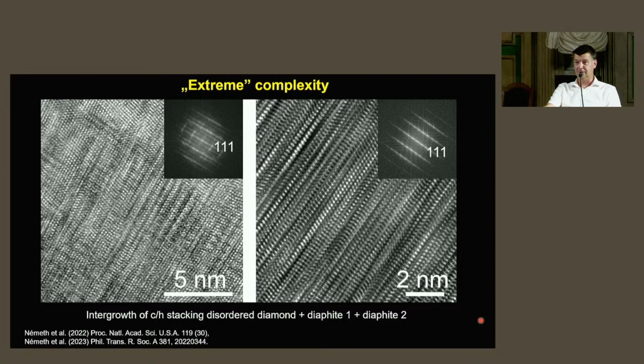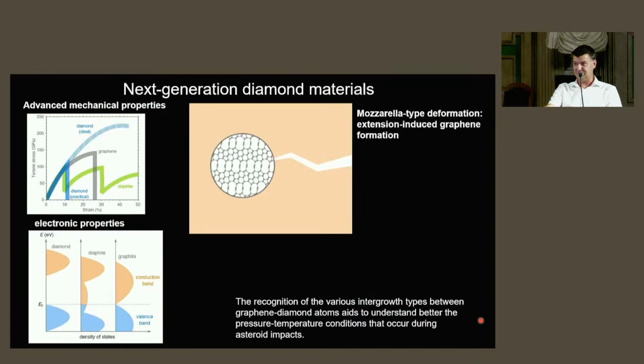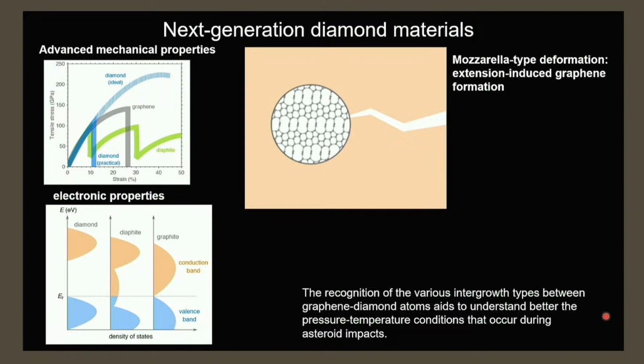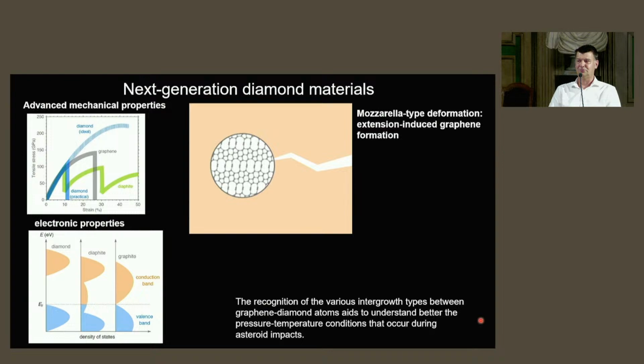Now, these diaphite structures have very interesting properties, even mechanical and electronic properties. In particular, as you know, diamond is a very hard material, but not ductile, so it's not suitable for applications which require the diamond to be ductile. According to calculation, ideal diamond could achieve even 45% longitudinal strain at an extremely high tensile stress of 200 GPa. However, real diamonds break much before that. In contrast, graphene can really reach 25% strain.